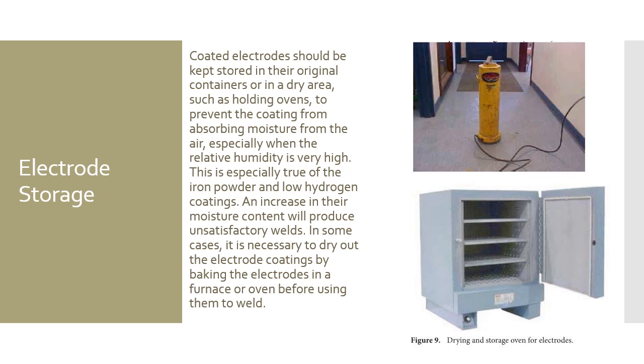rebake and recondition, I think is some of the terminology. But depending on what the code is and your manufacturer's recommendation on how to deal with the filler material, you use these ovens to store 7018 in them, and you can recondition it too. If it's been out for a certain amount of time, then you need to recondition it at a higher temperature to chase off the moisture and whatnot. You don't use these for 6010. You will ruin the 6010 and cellulose-based electrodes if you throw them in these ovens. So cellulose-based electrodes like 6010 need a certain amount of moisture in them to function properly.